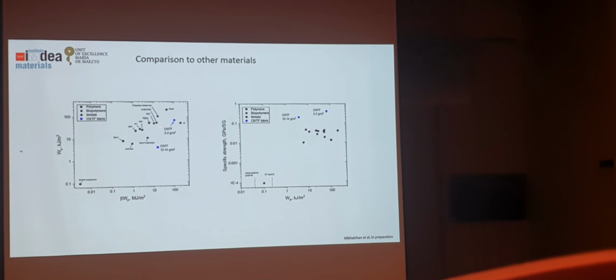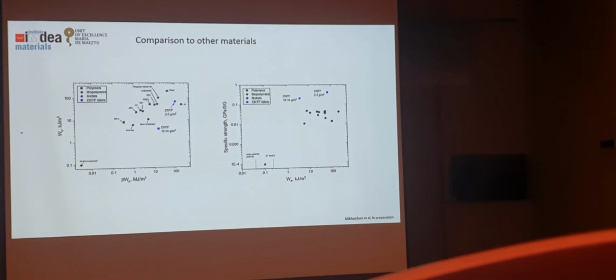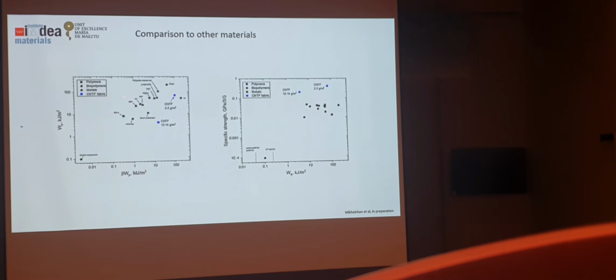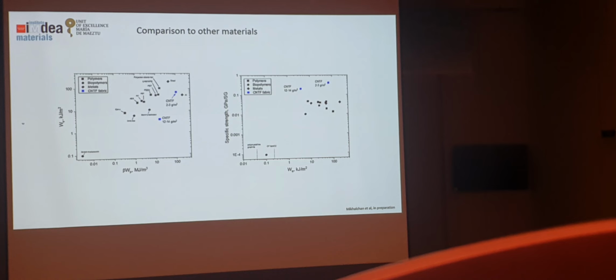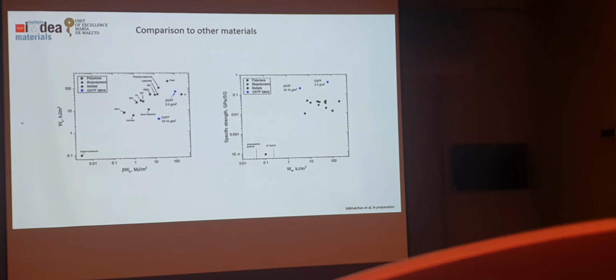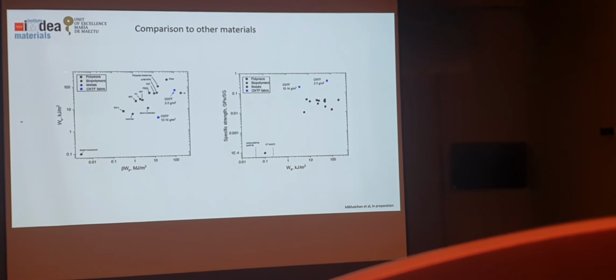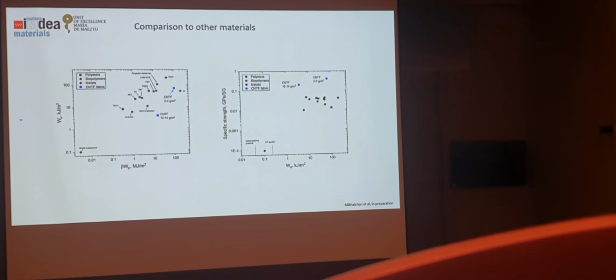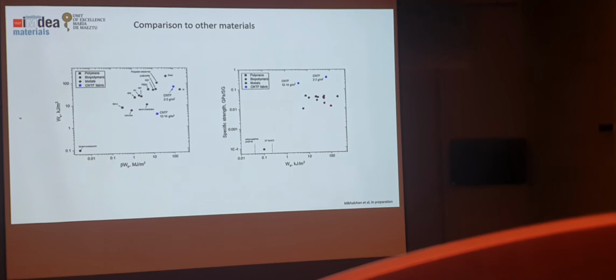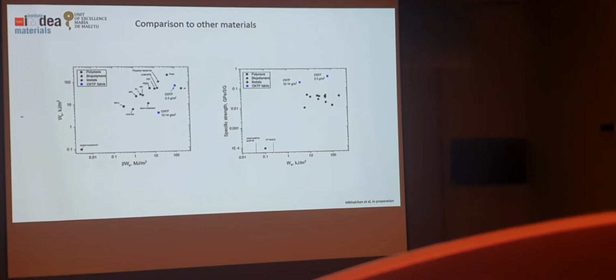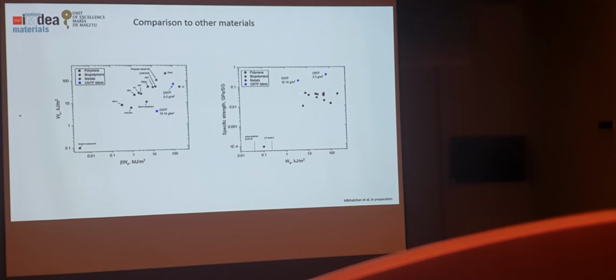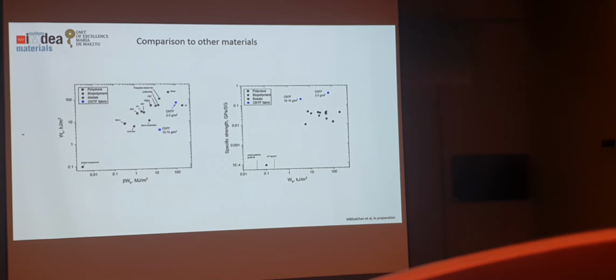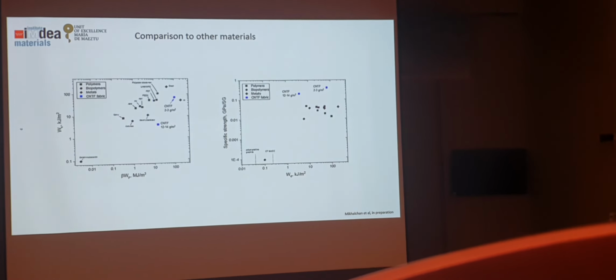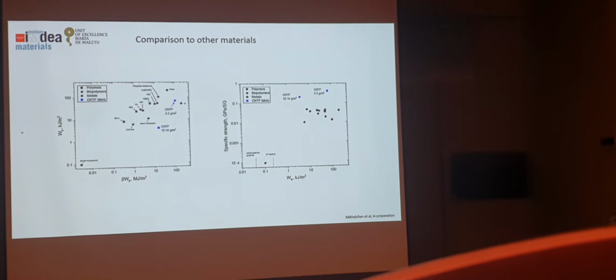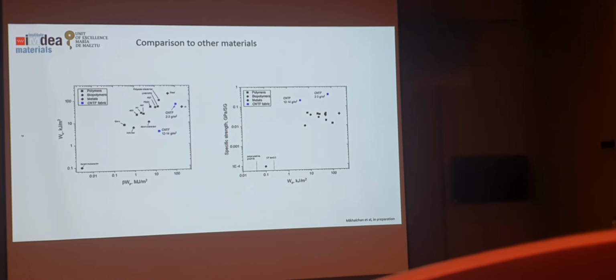And this is well in the range of tough plastics and even some metals. That really is very encouraging, and that helps understand why this material can handle recycling. Now, you can also think of another figure of merit, which is the strength against the essential work of fracture. Sorry, I've moved this axis to this side, and you can see, for instance, how they compare to some metals. The strength is higher, of course, normalized by density, but the essential work of fracture is pretty similar. So we are finding that these macromolecular structures have an inherent toughness. This was suspected, but now we're able to quantify it better, and that is quite key for recycling.